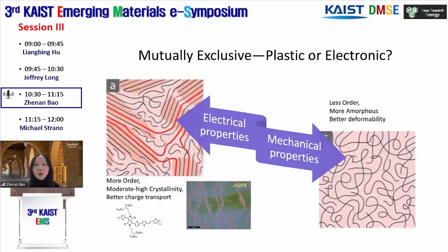But the key materials design challenge that we face is that now we want to incorporate skin-like properties into the electronic materials. But the traditional design concept for polymer semiconductors or polymer conductors is to design rigid conjugated structures so that it can facilitate the intrachain charge transport. And then the rigidity of the molecule also facilitates pi-pi stacking so that there can be good interchain charge transport. But this kind of molecular design results in brittle polymer thin films that form cracks at less than 25% strain.